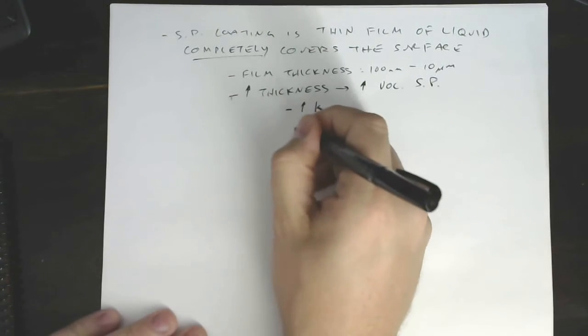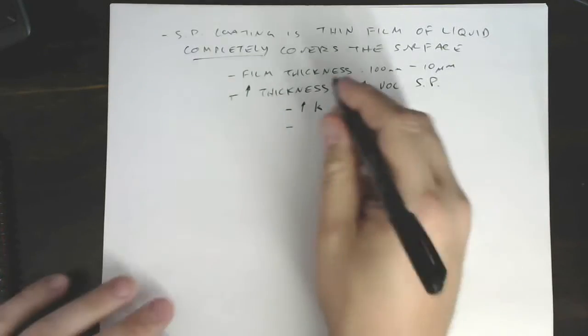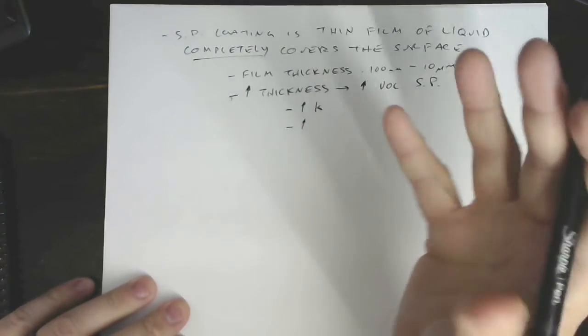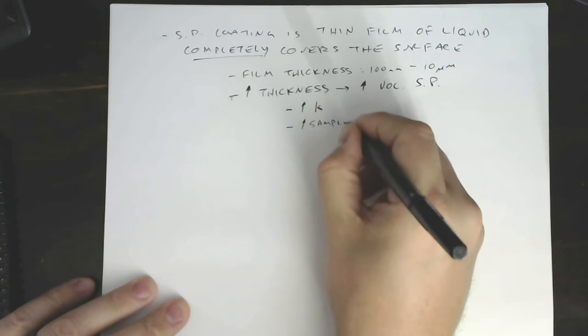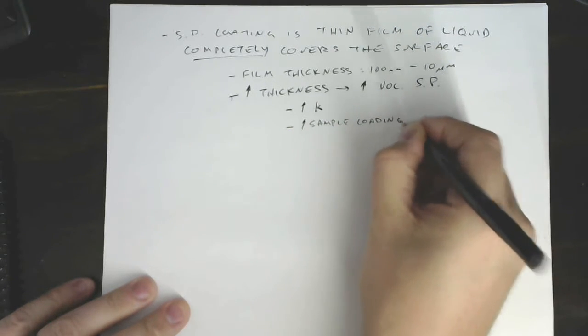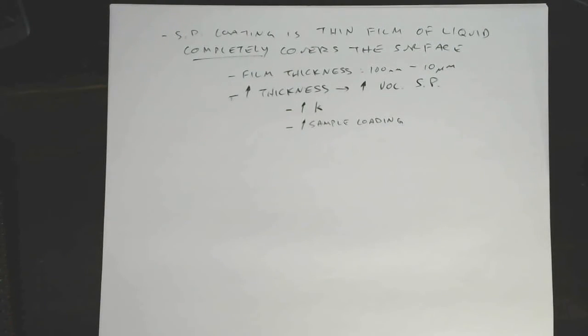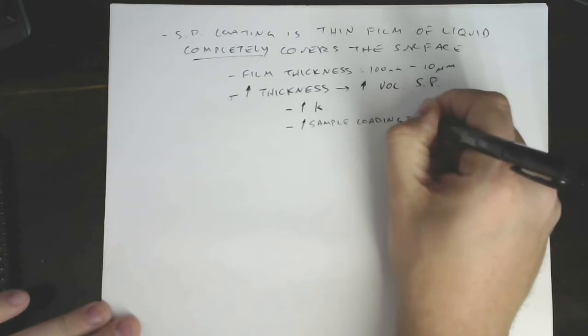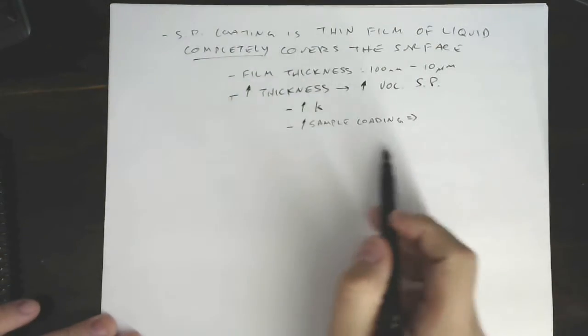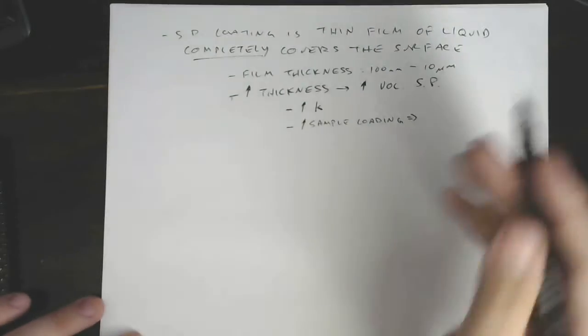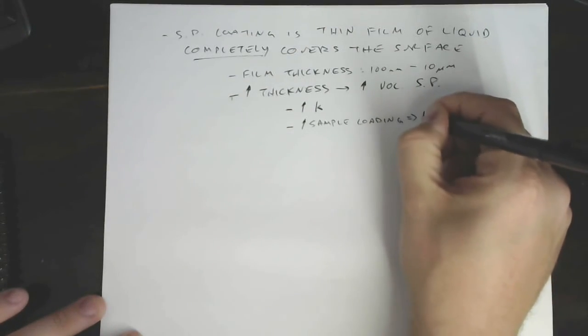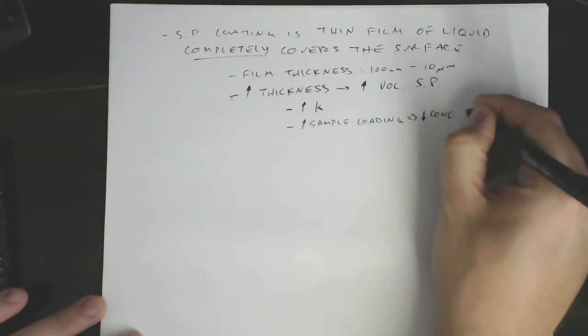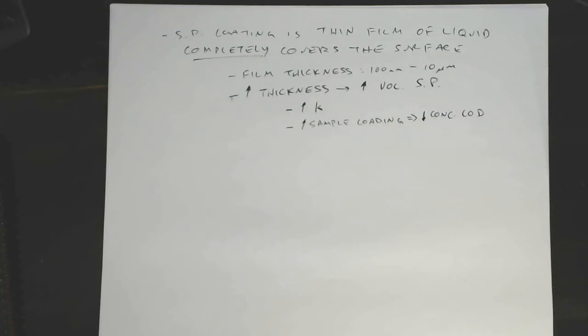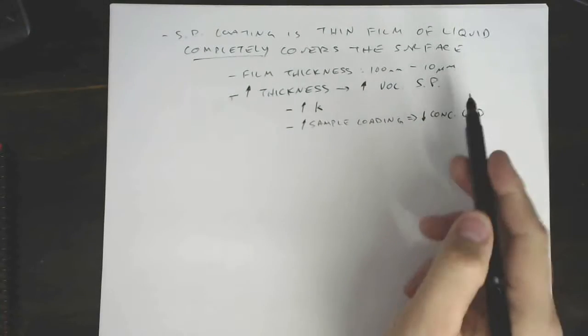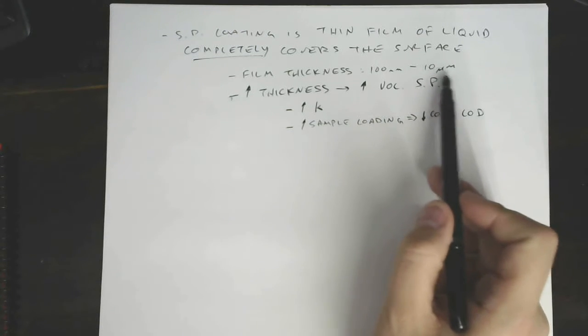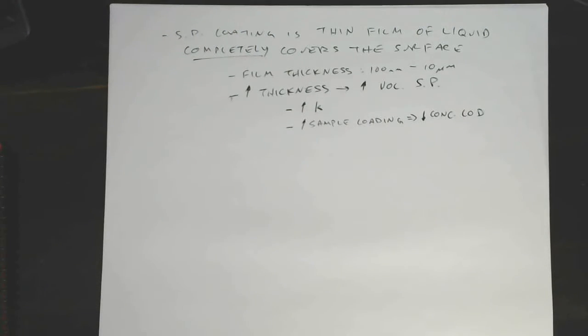It gives us another really neat property too, and that is it will increase our ability to load a lot of sample onto this column, right? It'll increase our sample loading capacity, the amount of sample we can inject onto this thing and still get nice effective chromatography. That's really neat because if we think about concentration limits of detection, the more sample we put onto the column, the more number of molecules we're going to be looking at the same low concentration, right? So this will decrease, and that's a good thing, concentration limits of detection. Okay, so increasing sample loading is one good reason why you might want to really drive up stationary phase volume. I really might want to work on this end rather than this end of the film thickness.